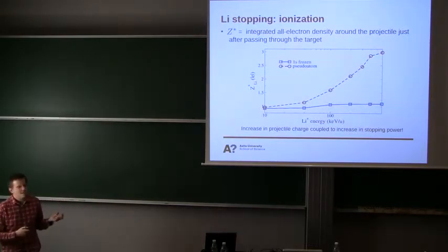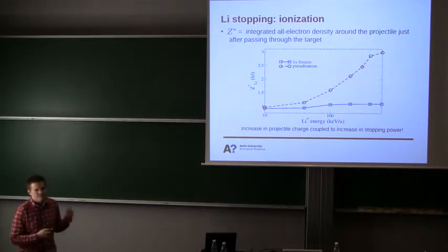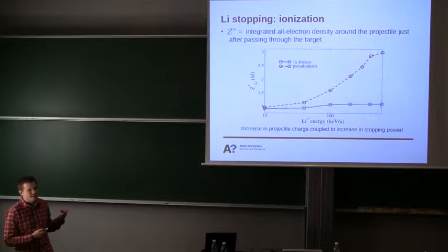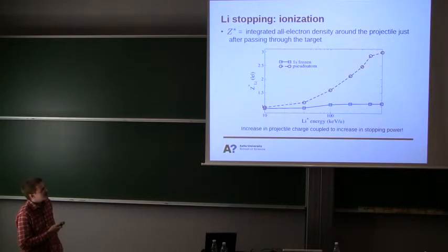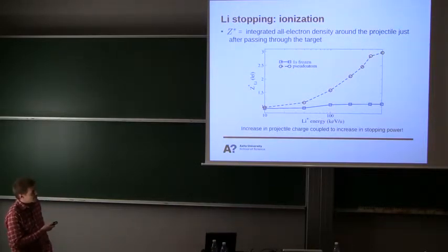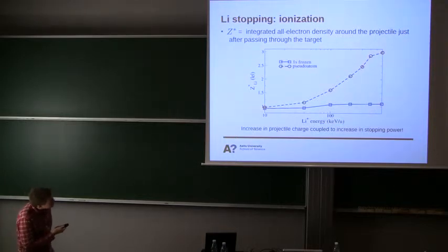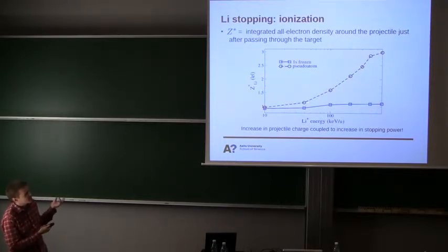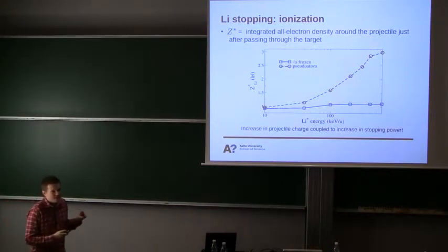Okay, and then we looked at ionization by integrating the density around the projectile after it went through the target. As you can imagine, with the 1s state frozen we have a single ionized projectile and nothing really happens. The projectile might have picked up some charge from the target, which explains the small differences here, but if you include the 1s,